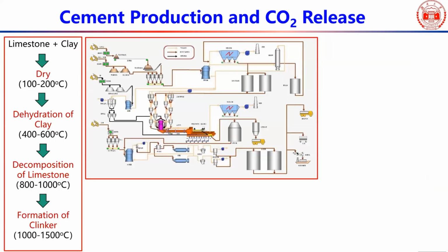And well, because in civil engineering our main basic material used is cement, right? So this is a basic flow chart of Portland cement production, and you can see during the production process, first the limestone and the clay get dried between 100 and 200 degrees C, and then dehydration of clay, then decomposition of limestone, and finally the clinker minerals will form between 1,000 to 1,500 degrees C.